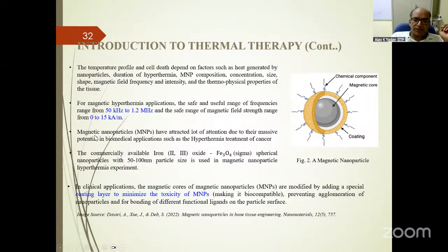Magnetic nanoparticles: what I'm using here is iron oxide, Fe3O4, taken from Sigma. This 50 to 100 nanometer particle size is used in the magnetic nanoparticle hyperthermia experiment. We have done some study here, and as you take a smaller size, around 10 nanometer, the SAR value was highest, maximum. But as you go lower and lower, the cost will increase.